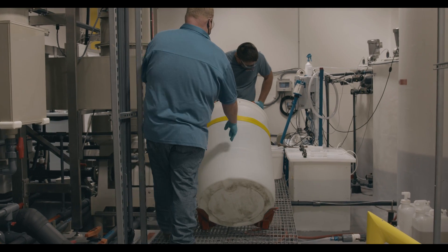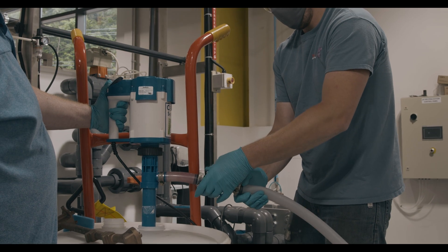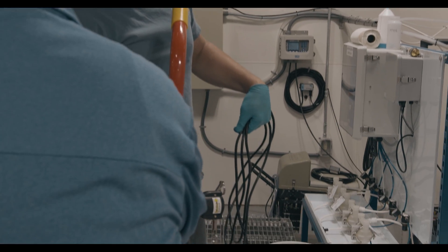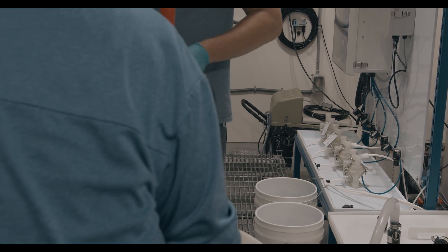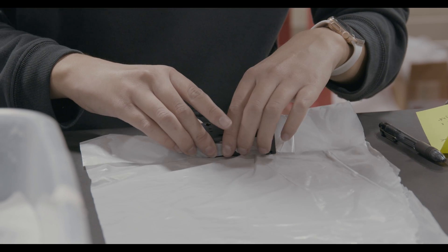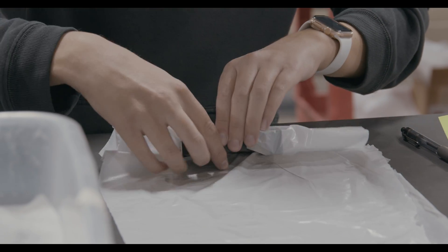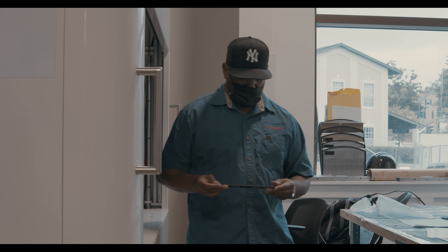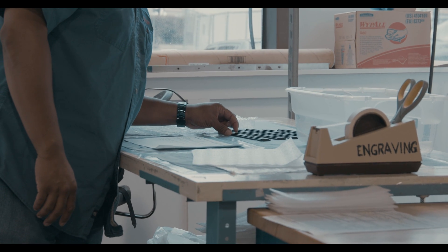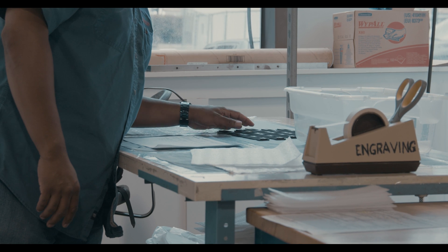We constantly monitor the chemistry to make sure the pH of the dye is correct, that the color end of the dye is correct, and by keeping our thickness tight by anodizing by surface area instead of by voltage, we get a very consistent thickness so our color matches almost across the board. I think the quality has increased and we're putting out a more aesthetically pleasing product to the customer because all of the parts of the assembly match.